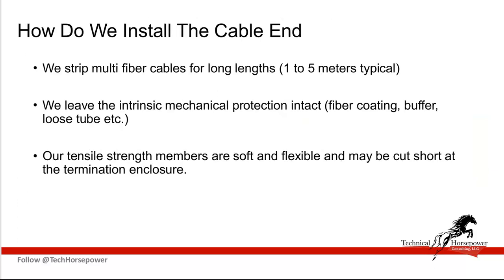So, again, we're stripping fibers for much longer lengths. Today, 1 to 5 meters are typical. On a high fiber count cable, that may actually be short. In some cases, we're stripping it to put the fibers and the tubes that they're in inside a splice case, and then stripping the tubes off for the individual fibers to be used in a fusion splicer or a mechanical splice application.